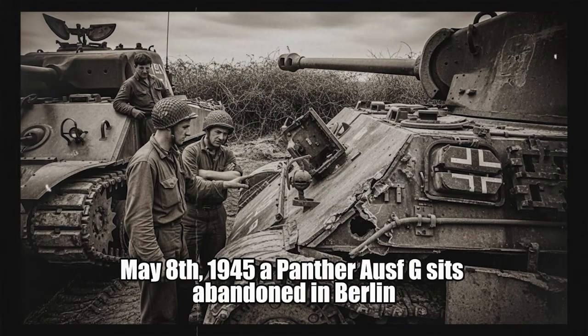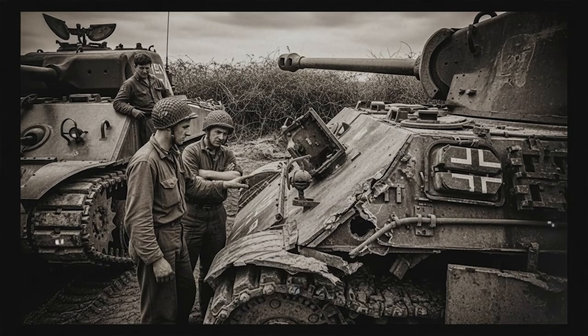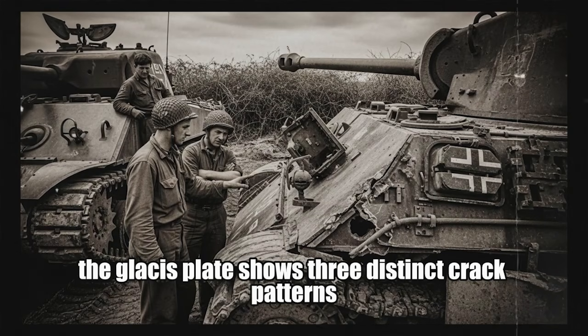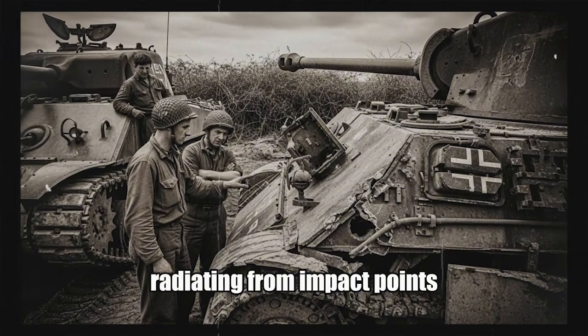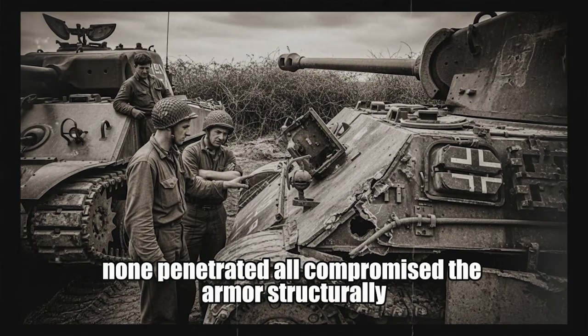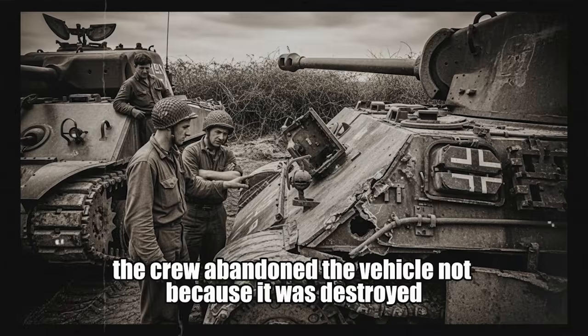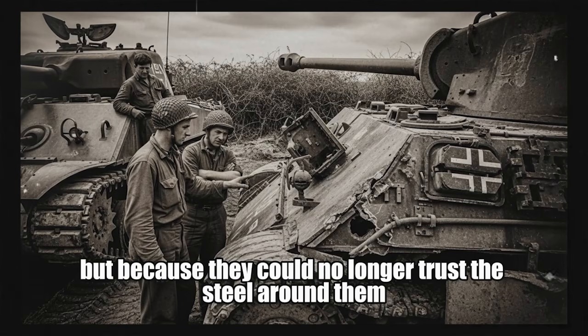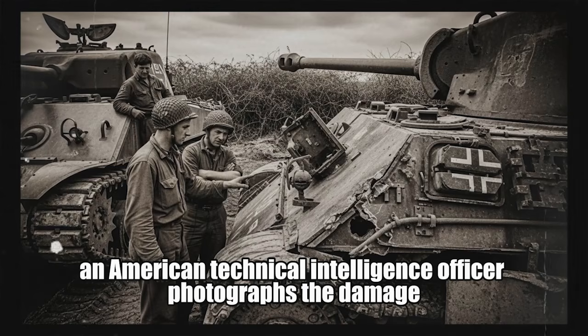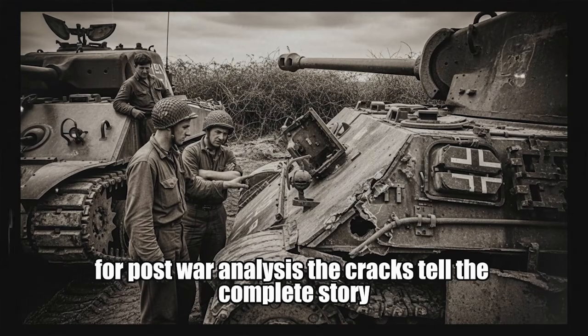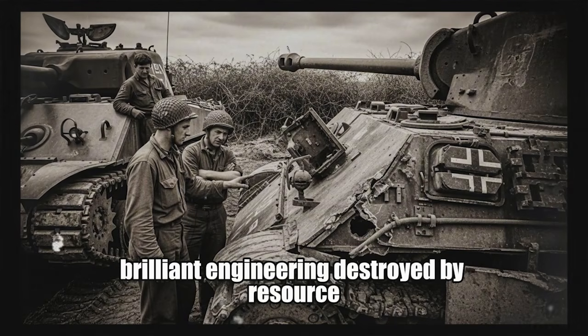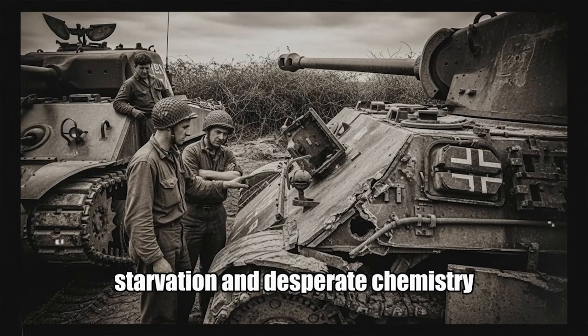May 8, 1945. A Panther Ausf G sits abandoned in Berlin. The glacis plate shows 3 distinct crack patterns radiating from impact points, none penetrated, all compromised the armor structurally. The crew abandoned the vehicle not because it was destroyed, but because they could no longer trust the steel around them. An American technical intelligence officer photographs the damage for post-war analysis. The cracks tell the complete story. Brilliant engineering destroyed by resource starvation and desperate chemistry.